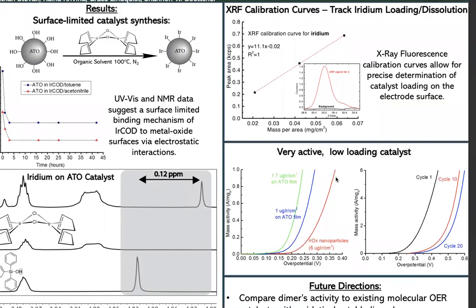Next, to test the electrochemical performance of these catalysts, we ran cyclic voltammetry experiments, where we swept between a range of potentials and monitored the current response in terms of mass activity, which is the current per unit mass. The earlier the onset of the current is indicative of OER onset.